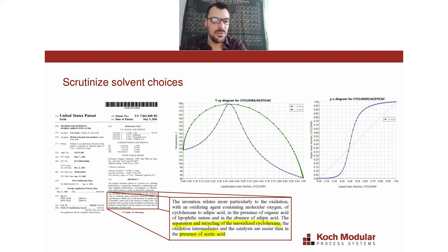Usually you want to completely segregate the solvent and the unreacted raw material so that you can add them back to the reactor at some prescribed ratio, not the ratio governed by an azeotrope. So process engineering might ask the question, is there a substitute solvent for acetic acid that would work just as well from a chemistry standpoint, but doesn't pose this difficulty during the recycle? We could still design a process to separate this azeotrope.